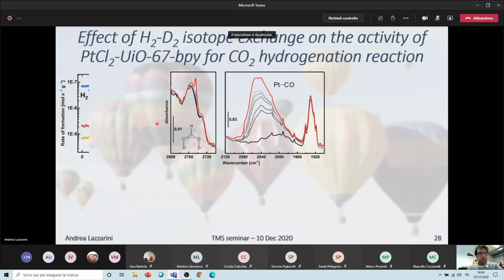But then, when we started dosing exactly CO2 and hydrogen, we were forming basically CO that was adsorbing on the metal nanoparticles, giving an infrared signal which is typical for CO adsorbed on metal nanoparticles, in this spectral area. But we were also observing the formation of small bridged formate species that was giving an extremely tiny signal. As you can see, it's like 50 times lower than this one.